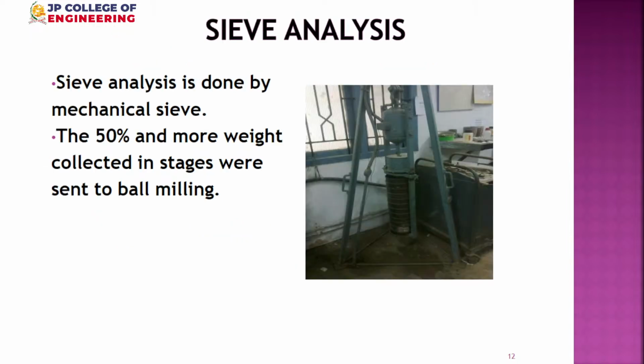Next slide, please. So this tells our preparation method. We obtained our fly ash from the Neyveli NLC plant, and then it was put through a sieve set. A sieve set is nothing but what our mummy uses for sieving rava or wheat atta. But here we have a series of sieves, from large openings at the top to very small openings at the bottom. In the top sieve you put the particles and then shake them using a suitable sieve shaker, and it will grade them. So we took the final very fine particles for further processing. From the sieve analysis we removed all the coarse particles and took only the fine particles. We went still further because the particle sizes we could find ranged from 100 micron to 50 micron and so on, but we want nanometer size. Therefore we have to go for further size reduction using ball milling. Next slide please.